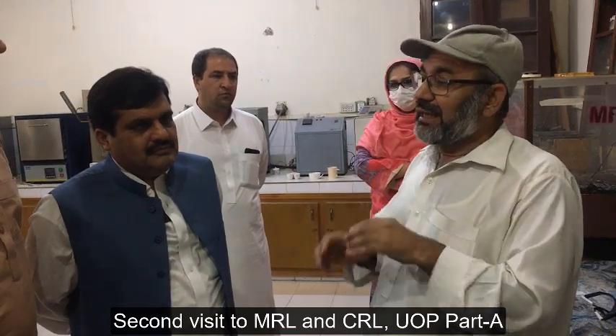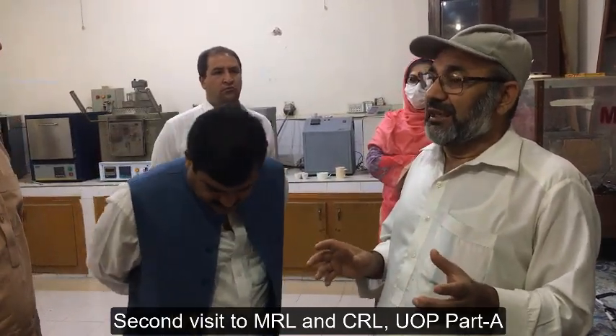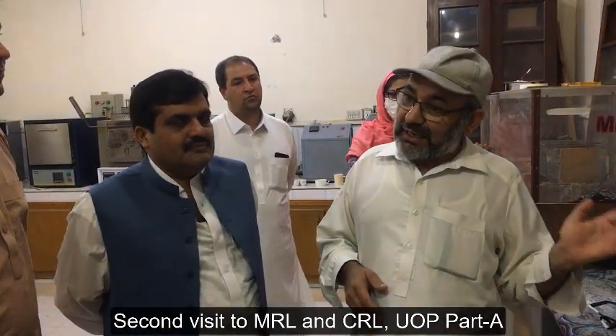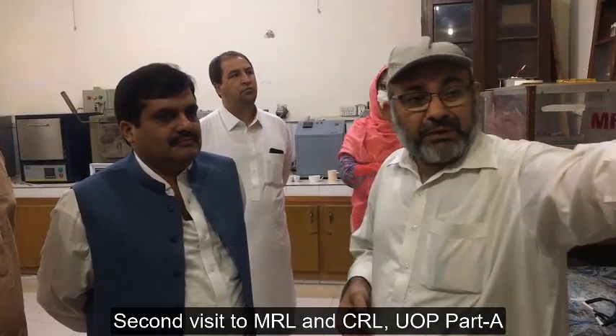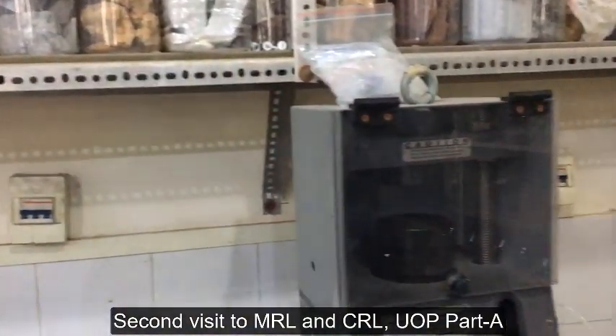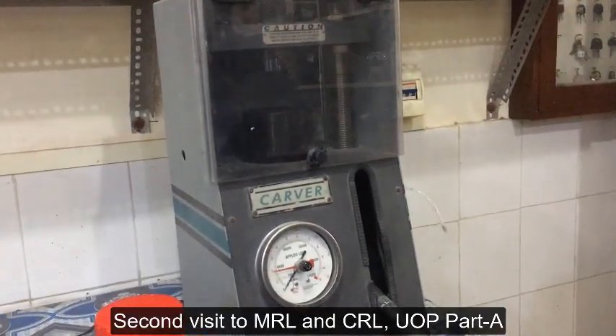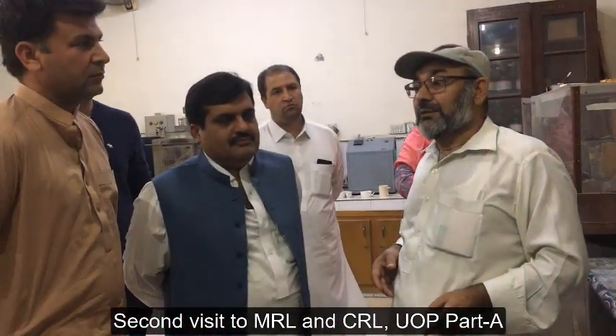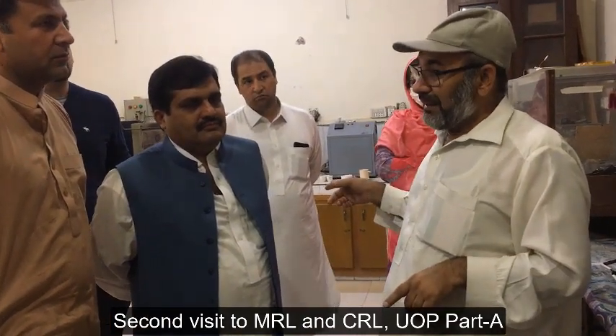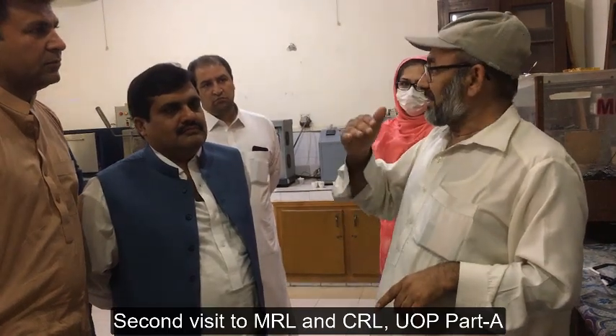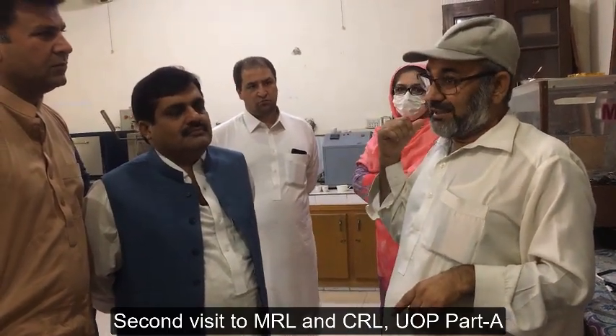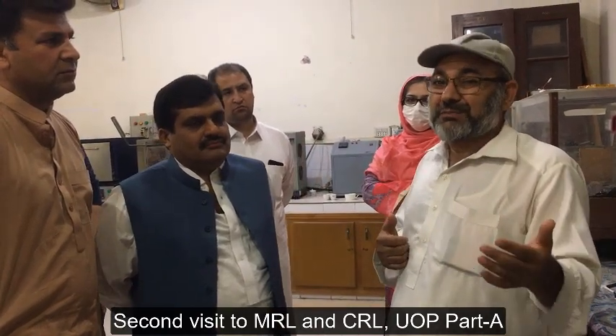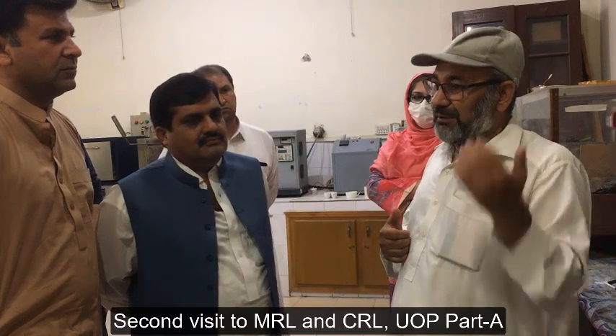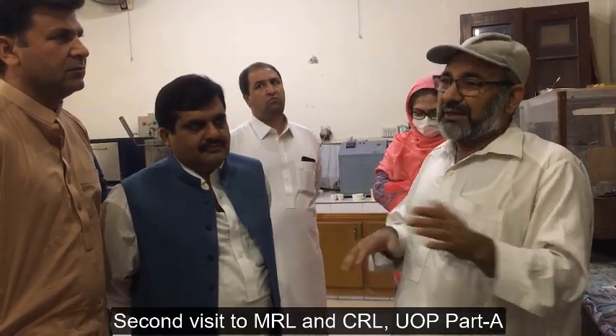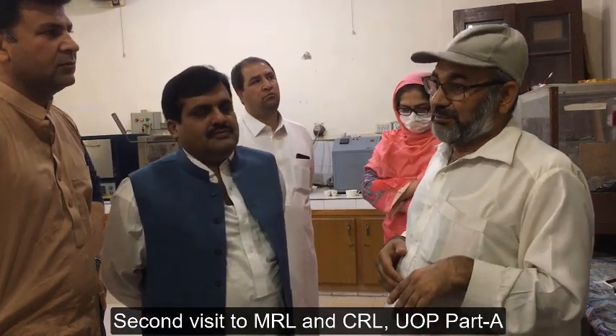After calcination, again there is a chance of agglomeration or anything like that. So we again mill them, again dry them, again sieve them, and then press them into the desired shapes, usually into pellets with this manual pellet press. After pressing, we sinter the material, and sintering basically enhances the density of the material, because the phase was formed during calcination, but sintering is not used for phase formation. It is basically for densifying the material, for making it hard enough for that particular purpose. And then we polish them and then take it to the properties which we want.